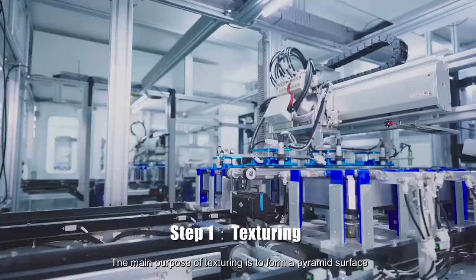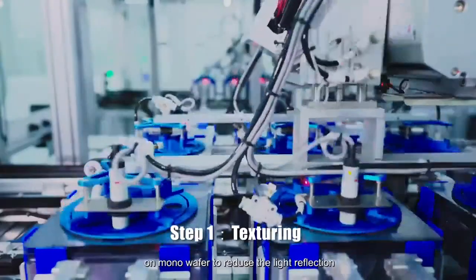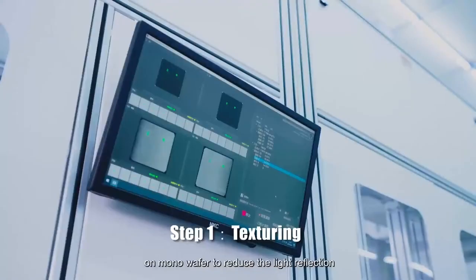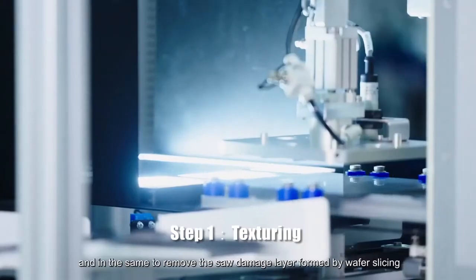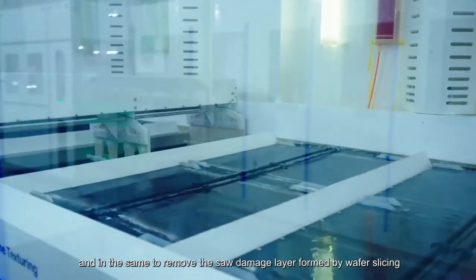The main purpose of texturing is to form a pyramid surface on the mono wafer to reduce the light reflection and at the same time to remove the saw damage layer from wafer slicing.